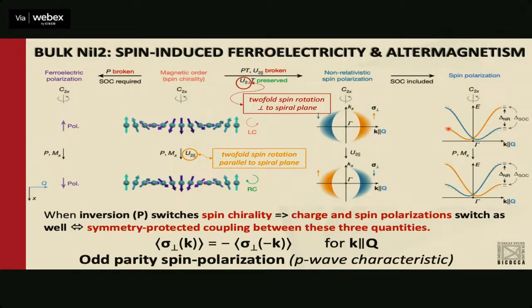For example, that's schematic, right? But if you plot the band structure along a direction in reciprocal space which is parallel to the propagation vector of the helix, you basically have a spin splitting here. Blue, for example, is spin up and orange is spin down. If you apply an electric field by which you switch the spin chirality, the spin splitting will also revert. You see here that orange is lying above blue, but if you switch the spin chirality, then blue is lying higher than orange. So by applying an electric field, you're able to control the spin texture.